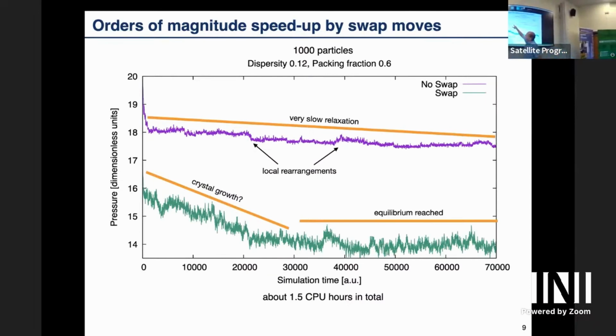And you see also these jumps. So apparently there are some local events where things rearrange and then it gets a bit more ordered. But overall, even after here 1.5 hours, we didn't get much below 18, so it doesn't go a lot. But if you do this swap, then immediately after a few seconds already you're at 16. So things are many, many orders of magnitude faster, and you can actually relax much better.